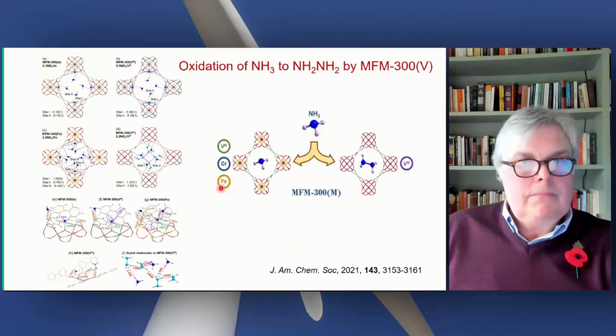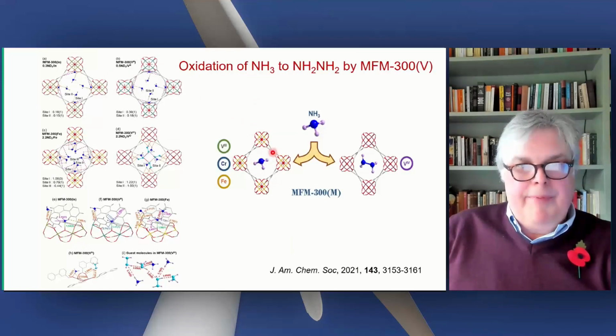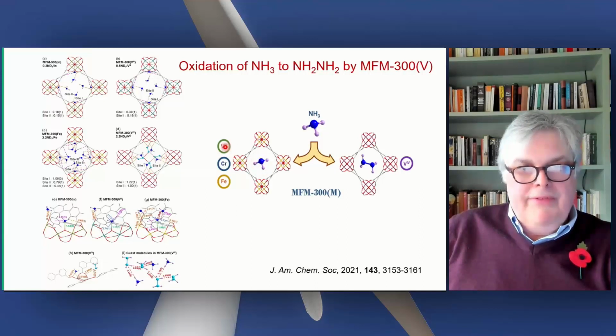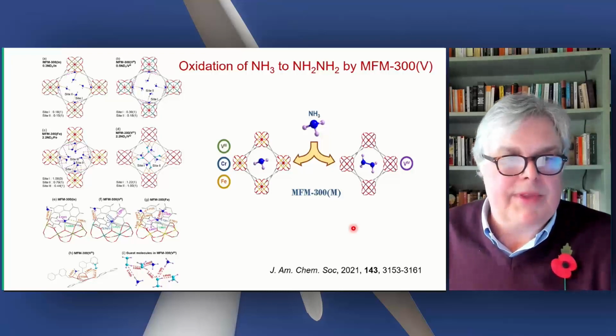Here is another piece of chemistry, which I think is quite exciting. You can take ammonia within the vanadium-3 system. The vanadium-3 goes to vanadium-4, and the ammonia goes to hydrazine. And you can follow this spectroscopically, you can follow this structurally, and see this chemical reaction taking place within the pore.